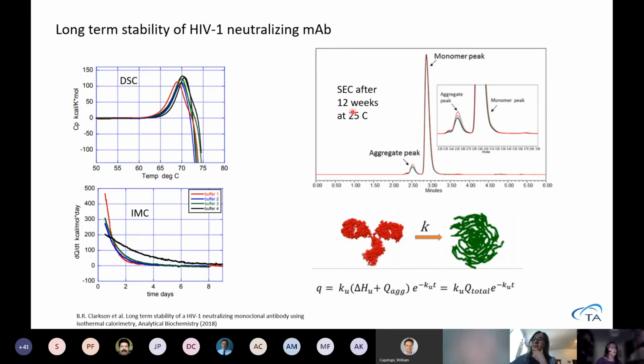This has also been stored on the shelf. You can see the time here is 8 days. This has been stored on the shelf, and then size exclusion chromatography has been made after 12 weeks. And we can see that if we increase the graph here, the aggregate peak has increased, or there is aggregate peak with the different buffers. These different buffers will correspond the colors with the stability measured in the isothermal microcalorimeter.